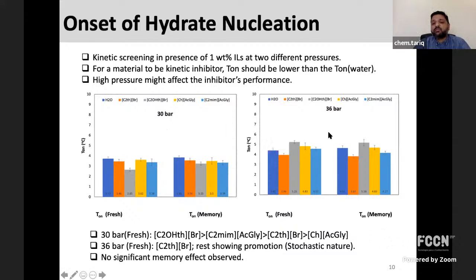So here you can see that all of them are showing that, and we performed this at 2 different pressures, 30 bar and 36 bar, because sometimes you can get different results, and that's what we also observed in this case. So at 30 bar, we see that hydroxyl thiouronium bromide is showing the best results, and cholinium acetyl glycinate is showing the least result. At 36 bar, only thiouronium bromide is showing the inhibition, the rest are showing promotion. Which can be because it has been reported several times that high pressure might affect the inhibitor's performance, and sometimes it could also be because of the stochastic nature of hydrate formation.